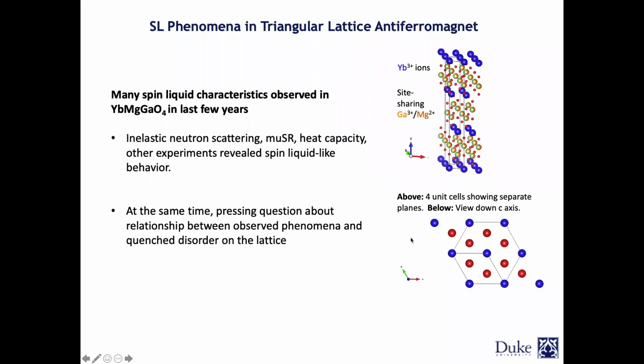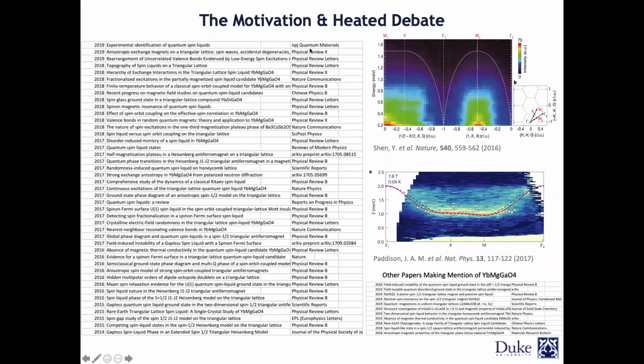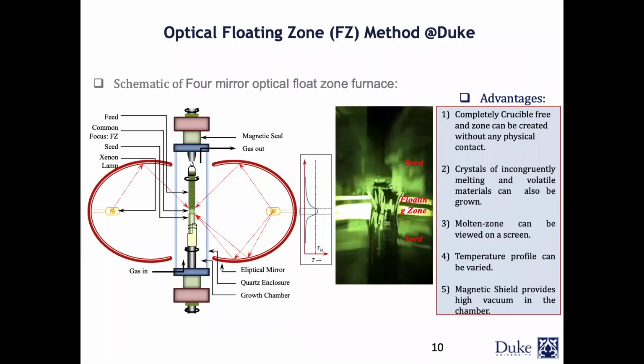Okay, so these are only the papers that have been published on this compound from 2015 to 2019. I stopped actually adding to this after 2019. But there are another 10 or so added to this. And what is interesting is that this debate and so much discussion about this compound, it's still going on. So it is very much a hot topic, and there's still a lot of discussion about it. And it motivated folks to actually start not only revisiting their theory, but also designing new compounds in which, for example, the chemical disorder is less or more, to understand what that chemical disorder in the insulating layer is doing. So we were also interested to study this compound as well, and we started to try to grow large, high-quality single crystals of this compound. So the very first thing that I always explain to my team is that the quality of the sample is very important.